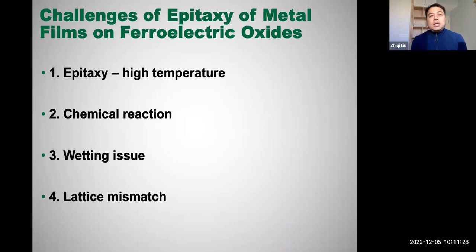The best heterostructure we like to have is epitaxial heterostructures. For example, if we can epitaxially grow single crystalline ferromagnetic metals onto ferroelectric oxides, that would be cool. Because in this condition, when you apply an electric field, the compressive strain or tensile strain will be exerted along certain crystallographic directions, and then you would have the largest modulation.